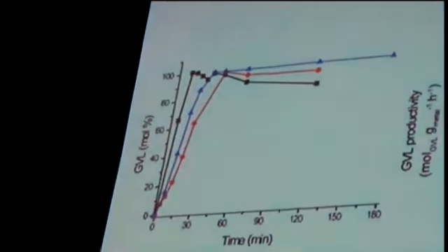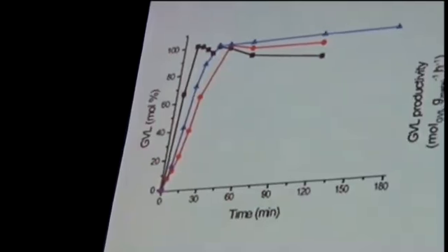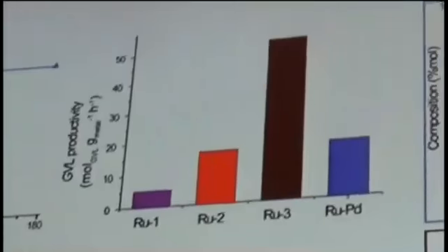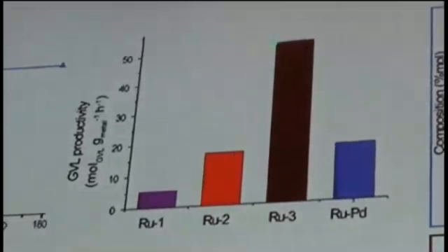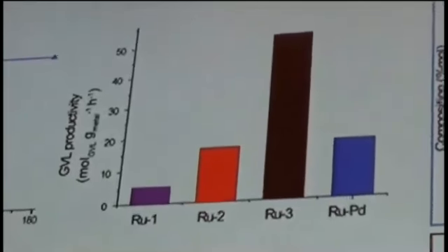So what about this third catalyst? The modified impregnation one, ruthenium-3. If we omit the half a molar of HCl in the synthesis method, we actually get a monometallic catalyst that is exceptionally active. In this particular case, we have a 10-fold increase of activity compared to our standard ruthenium catalyst.